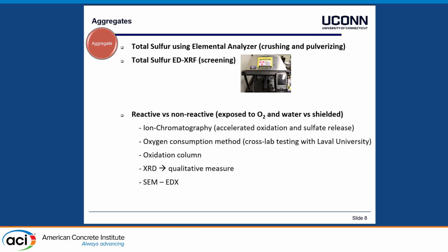You can use, for example, ion chromatography, accelerate your reaction, putting those aggregates in a hydrogen peroxide solution, for example, so having like an oxidizing agent in there. Then sulfates are getting released and you measure the concentration of sulfates. Or with the oxygen consumption method from the University of Laval. So we are also involved in a cross-lab testing with them soon. I hope this is coming. And at UCONN, we have developed some oxidation columns to look at the reaction rate. You can also qualitative measure the presence of pyrrhotite with XRD or using SEM and EDX. You have seen some pictures here prior to this.